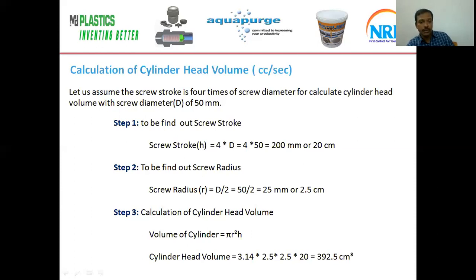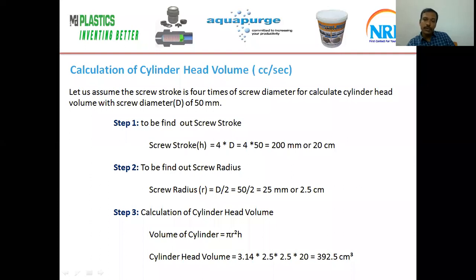Second, we have to find out the screw radius. Screw radius equals screw diameter by 2. So here screw diameter 50 by 2 equals 25 mm or 2.5 centimeters. After finding out the screw stroke and radius, finally we can find out the cylinder head volume. Volume of cylinder equals pi r square h. So cylinder head volume equals 3.14 into 2.5, 2.5 into 20. So for a 50 diameter screw, the cylinder head volume is 392.5 cubic centimeters.